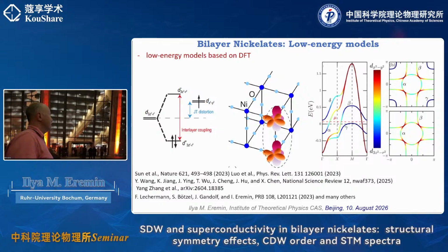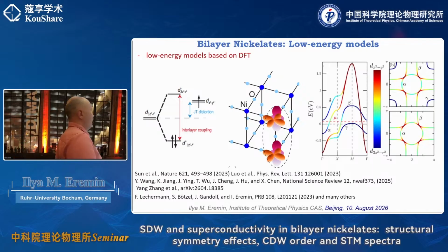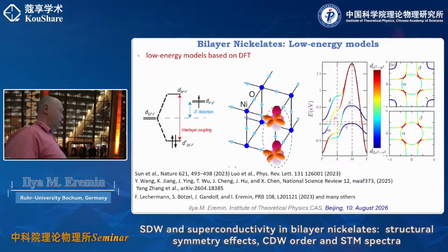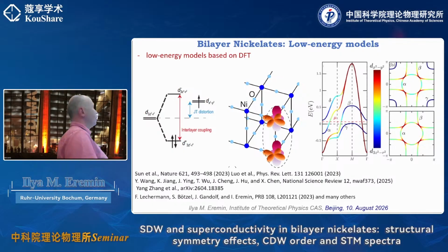And the strong hybridization yields a strongly split structure, so you can work in this mirror symmetry. You can use this layer structure and introduce a mirror symmetry, and introduce mirror symmetric or anti-symmetric combinations of the electronic states, and then you end up with 4 bands, so 2 orbitals, 2 layers. If you diagonalize it, you get 4 bands. And then you can still identify, despite the hybridization, the bonding dz²-like orbital